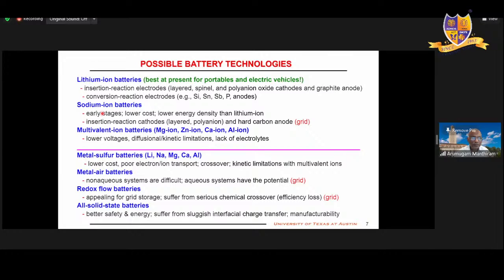So now let me say a little bit about this. I pointed out earlier, when you go from sulfide to oxide, the voltage is increased from less than 2.5 volt to 4 volt. And with the same ion, when you go from an oxide to a polyanion, the voltage again increases by more than 1 volt. So from these oxides to these, the voltage increases because the polyanion units have more covalent bonds. So the iron-oxygen bond will become less covalent, more ionic. So it is not raised that much as an antibonding level. So it is lowered. So the voltage increases.